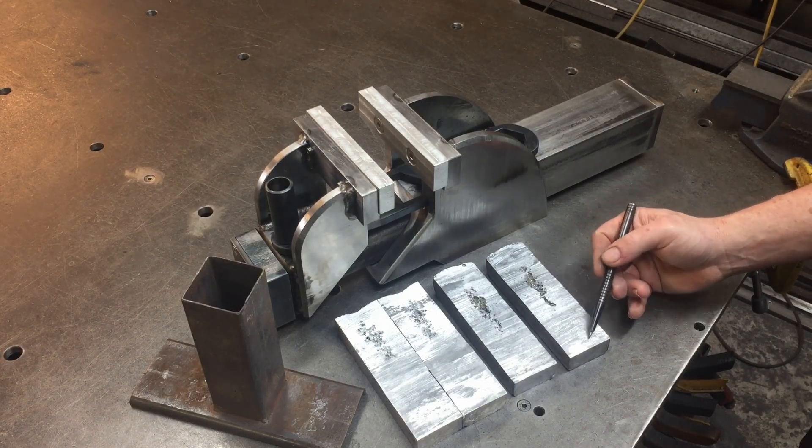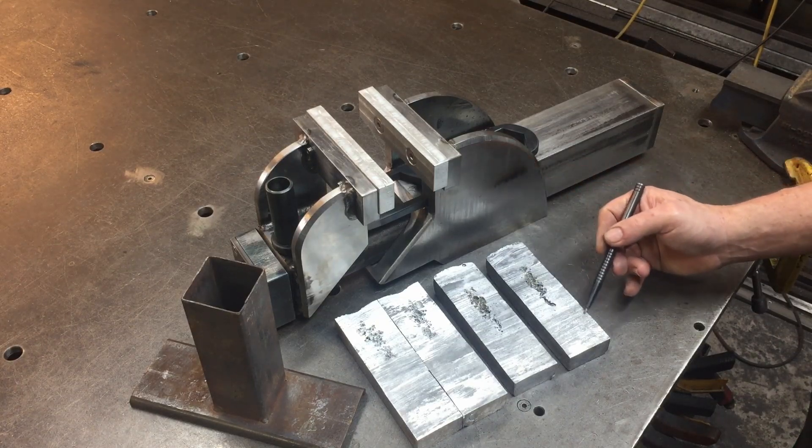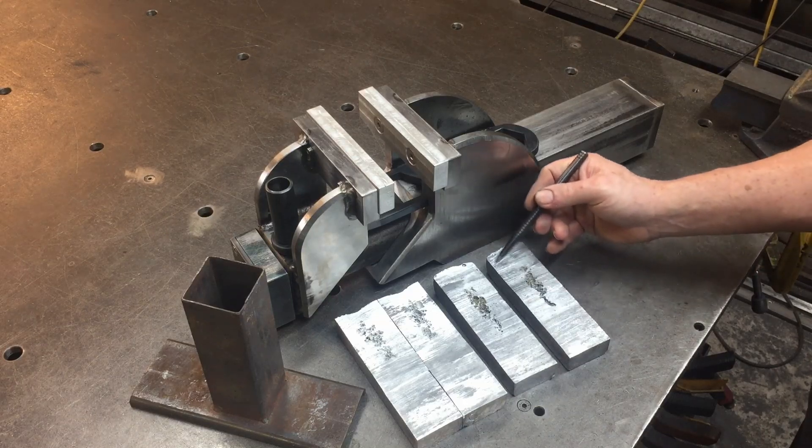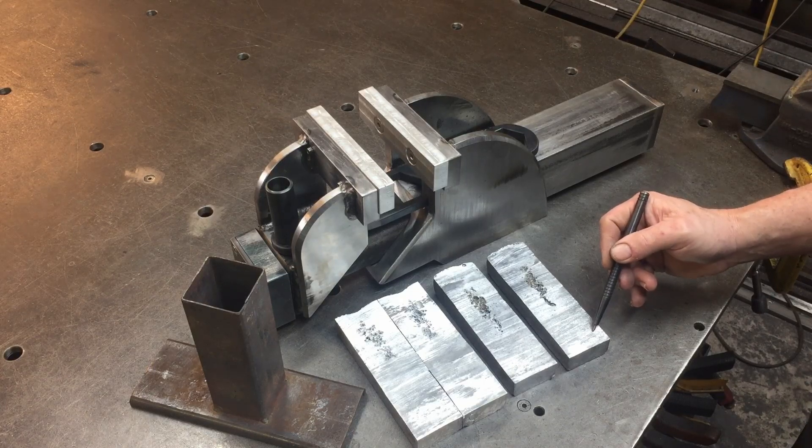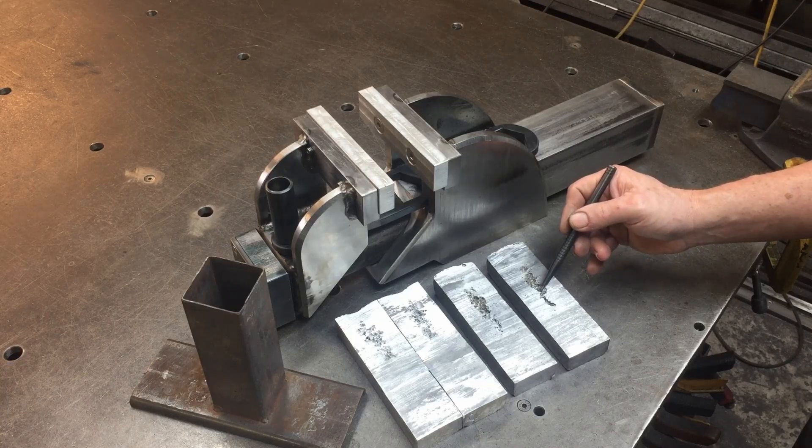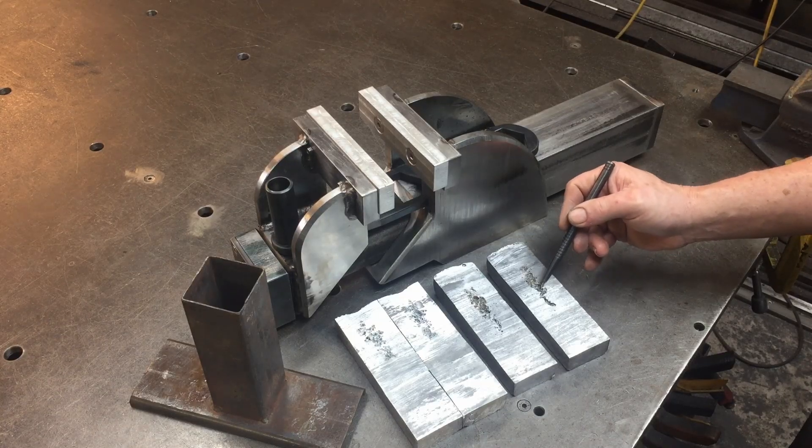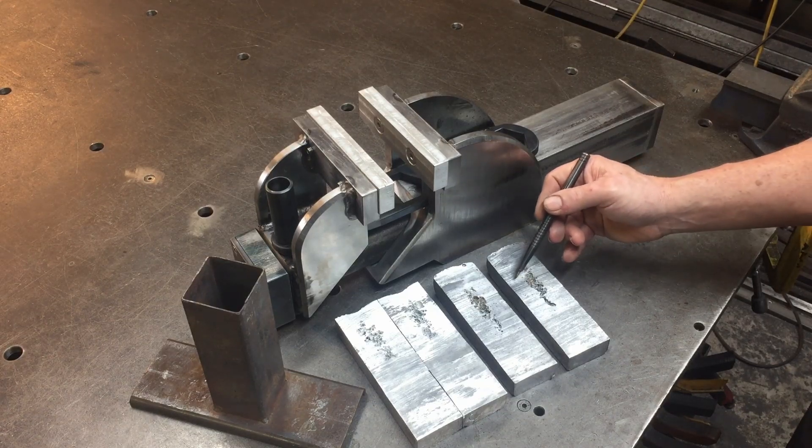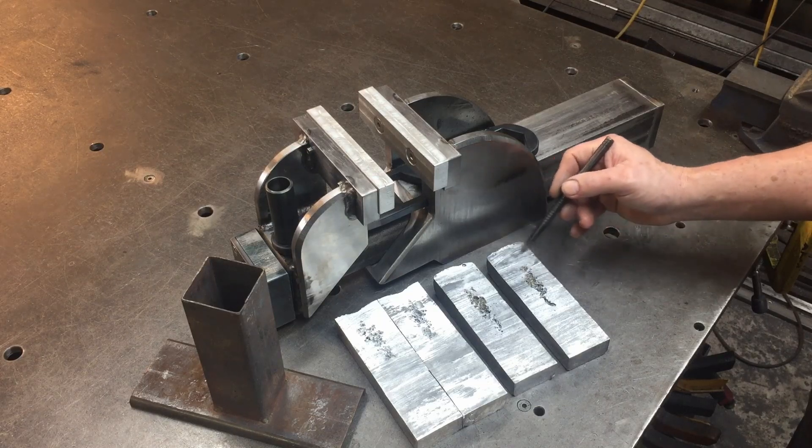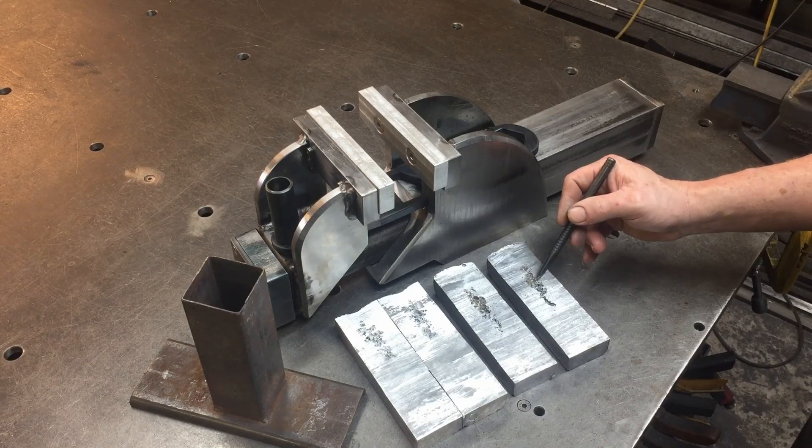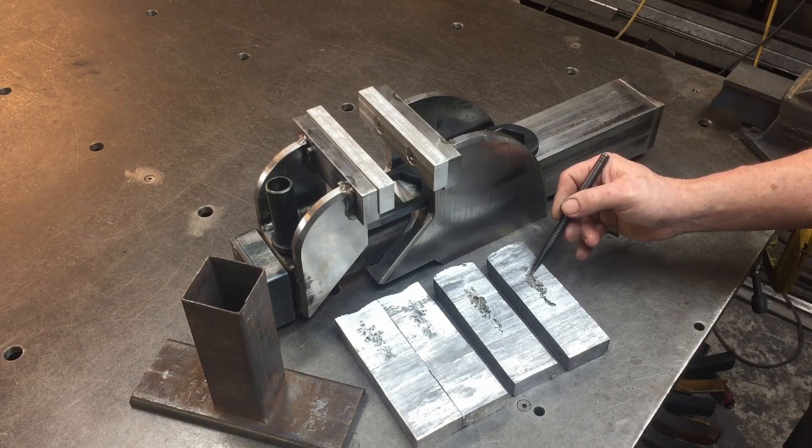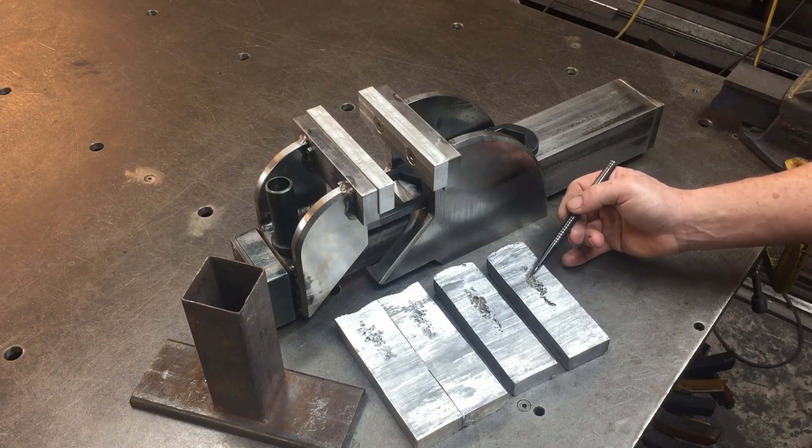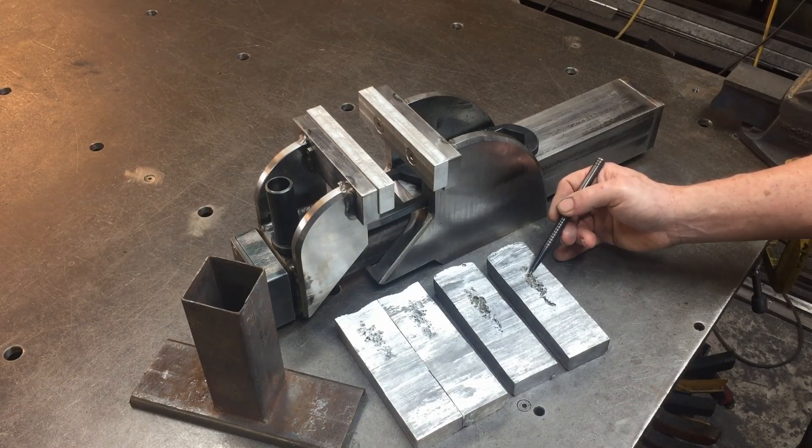I'm thinking it's been poured into the mold, the aluminum around the outside here starts to set and go hard, whereas the inside may be still liquid. As that starts to set and it starts to shrink, it can't pull in from these outside areas because they're already set. So it doesn't have any choice other than to cause a vacuum in here. I think that's what this is - it's the only logical answer I can think of to be honest.